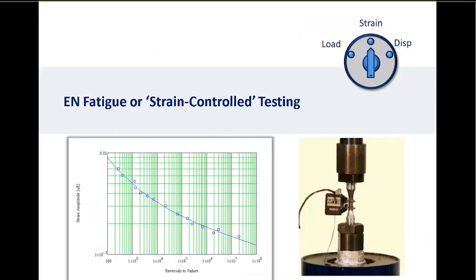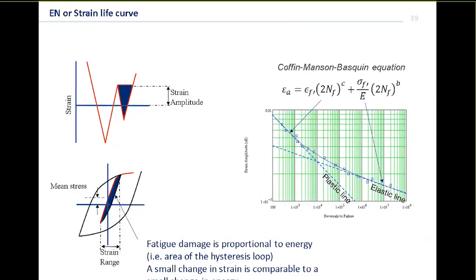So how do we test those? Here you can see what happens. Our elastic line is the Basquin equation, but now on the y-axis it's strain rather than stress. If we look at the Basquin equation, all we've done is take the SN curve and divide it by E, Young's modulus, to turn it into an elastic strain. What we've then done is add this other part, the Coffin-Manson part, epsilon f prime times 2Nf to the power c. That's what we call the plastic line.